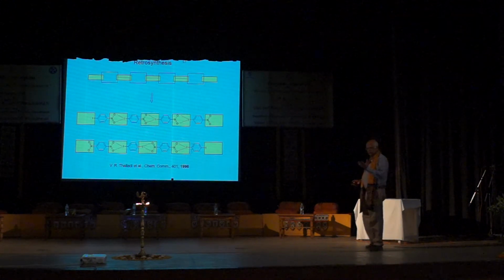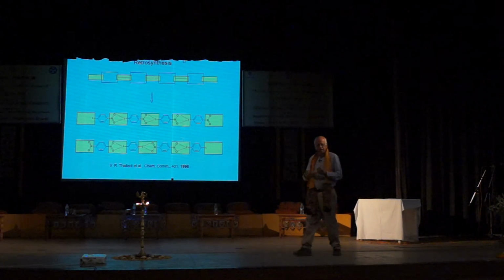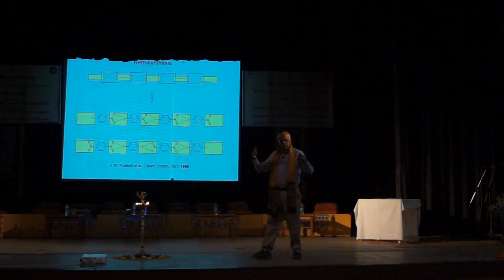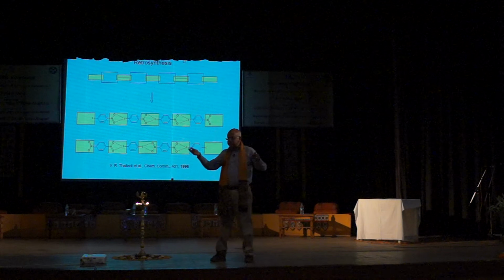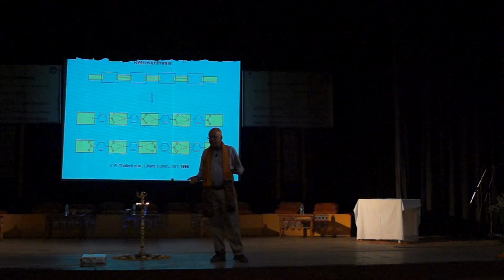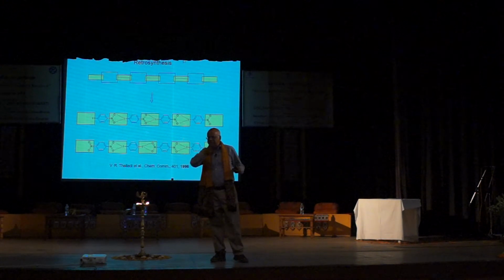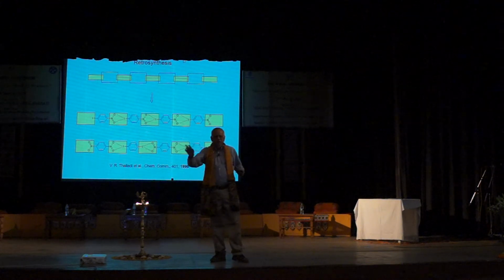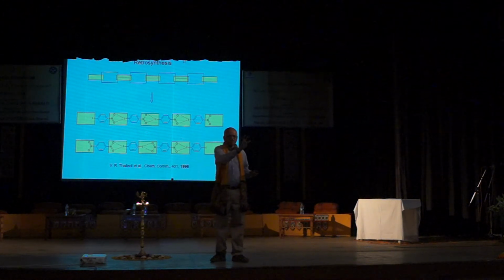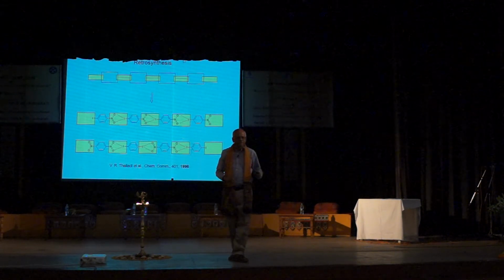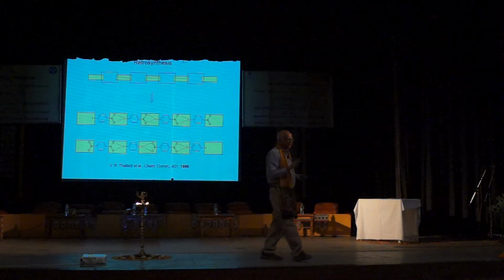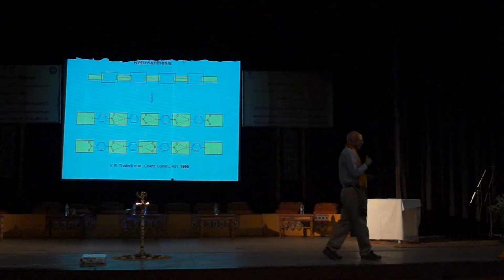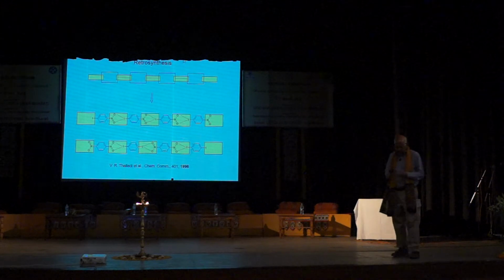So this is another thing I'm saying. The one component and the two component crystals have the same crystal structure. So both of them essentially are linear things assembled with this synthon. It is just that the sense of the synthon is reversed in one case. So this iodo-nitro is another synthon which we have, you can call it like a supramolecular reagent.